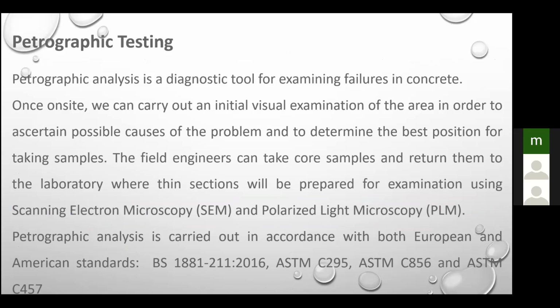Petrographic analysis, as you see, is a diagnostic tool for examining failures in concrete. So first the visual examination is carried out in order to ascertain the possible causes of the problem and to determine the best position for taking samples. And then you are sure that from a particular zone or position you have to take the samples, and then core samples, and take them to the laboratory for petrographic analysis.